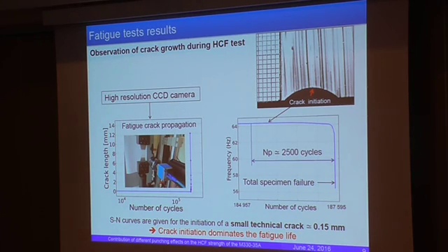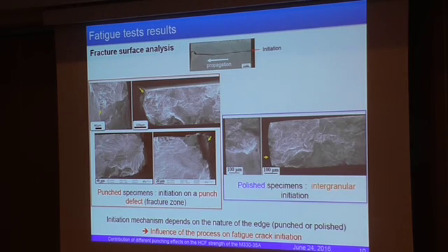I will just say a word about crack propagation. To say it short, it's very fast. It takes about 2,500 cycles for a 0.15 crack to propagate up to the final failure. So all the results I presented earlier are given for crack initiation. That's why we looked closer at crack initiation sites. All cracks initiated on the edges, and for punched specimens, whatever the heat treatment, they always initiate on a punching defect located in the fracture zone. I will come back to this point later. For polished specimens, crack initiation is intergranular.